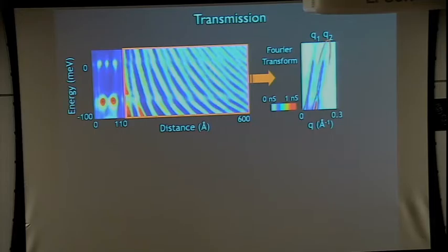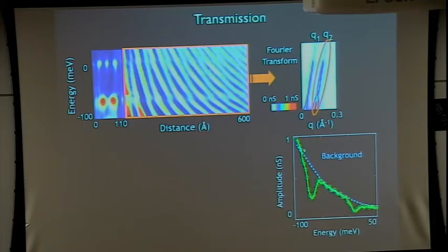Let me show you the line cut. So this is the signal of this scattering wave vector, and you can see that there is this suppression in the reflectivity. So essentially, this is a nice signature that the surface states for these antimony states, unlike copper, you can repeat this experiment in copper, have some finite degree of transmission, even though there is a very large atomic scale scatterer here, just an atomic step.